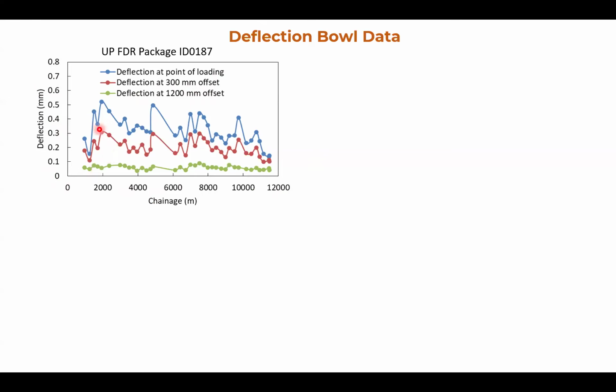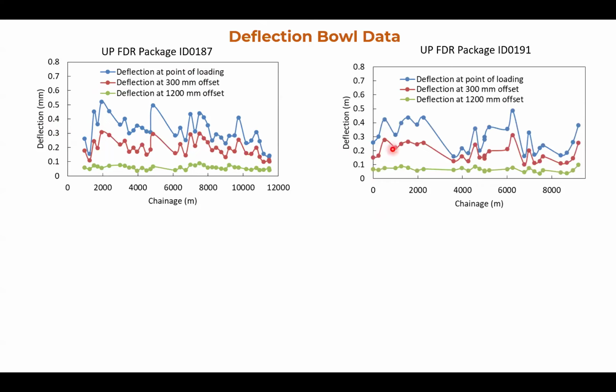This figure shows that there is a high variability in the deflection data. Here you can see the deflection can vary within a few meters. Let's say here the maximum deflection was 0.3, but at the next chainage it is 0.15. Due to this being an in-place stabilization method and the wide variation in the gradation, that reflects in the huge variation in the deflection data. This is corresponding to UPFDR package ID 187, but similarly, for just a few candidates, I'm trying to show the raw data from the FWD testing.